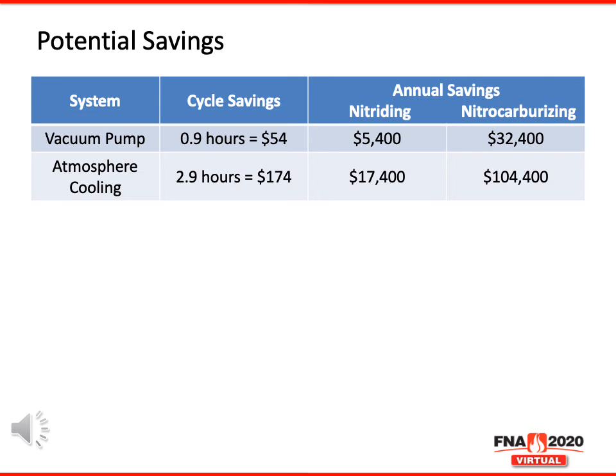And then with the atmosphere cooling system, it was just under 3 hours worth of time saved. Again, at $60 an hour comes out to about $174 per cycle. And again, over the course of a year, you can see just over $17,000 for the savings on a nitriding cycle, and a significant savings, over $100,000 on running nitrocarburizing cycles. Again, just by eliminating the amount of time required to complete those cycles.